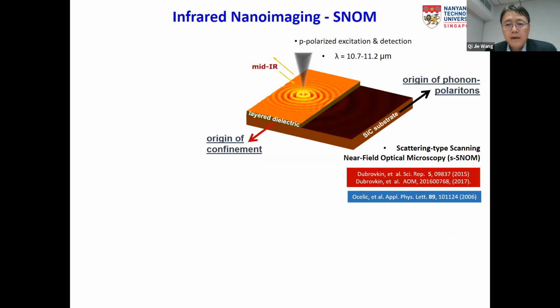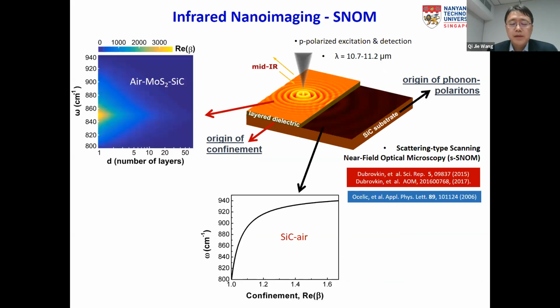Okay, and here we use a SNOM system. I believe all the audience have a good knowledge about such near field scanning optical microscopy system. That's the s-SNOM system we use. Okay, and basically we need to measure the interference fringes of the Phonon-Polaritons launched onto the sample, which was formed by the forward propagating Phonon-Polariton and backward propagating Phonon-Polaritons.